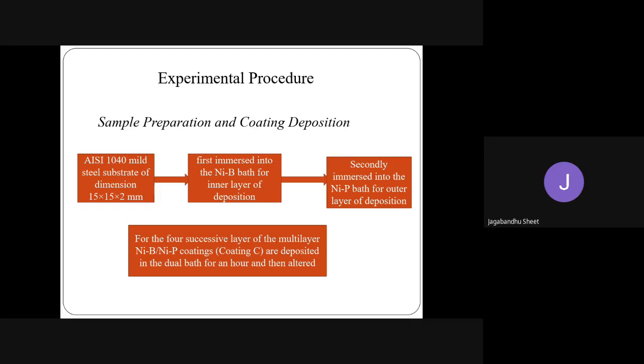And this is our experimental procedure. First we prepare the samples. For the sample preparation, a mild steel substrate is used, of AISI 1040 grade. Two types of samples are prepared: one is the square sample and the other is the pin sample. The square sample dimension is 15 x 15 x 2 millimeters. The square sample is used for characterization, measuring the microstructure and hardness values, and the cylindrical samples are used for the tribological test.